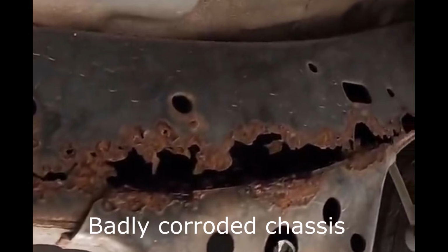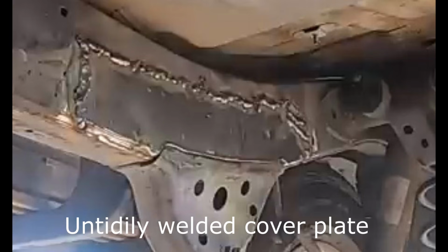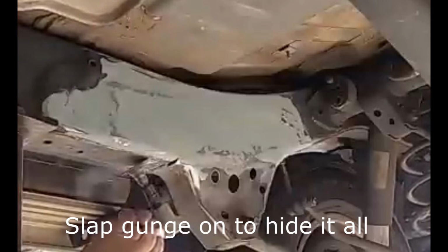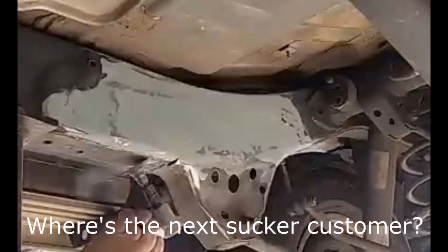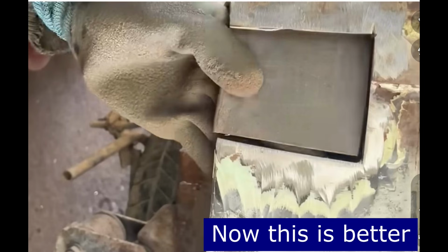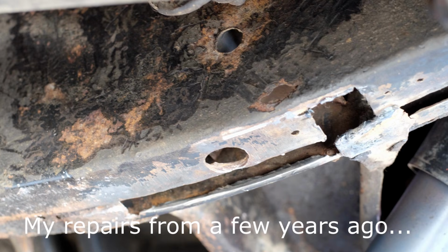So how should this repair have been performed? Well, firstly, it's never acceptable to slap a cover plate over rusty metal. You need to cut away the affected material first, then let in a plate and do a single-sided butt weld all the way around. And if the weld is good, by which I mean you get good penetration and no defects, it should perform perfectly satisfactorily.